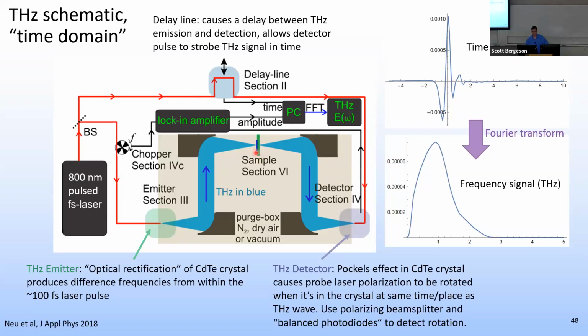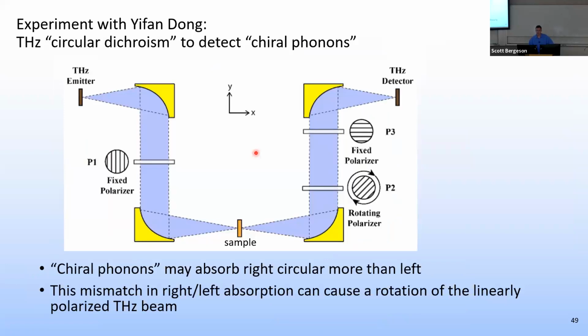We're interested in this because one of the thoughts is that these chiral materials will have what are called chiral phonons. Chiral phonons are oscillations of the atoms in the material that form a rotational pattern as they oscillate. Chiral phonons may absorb right circular terahertz more than left circular terahertz, and this mismatch between right and left absorption can cause a rotation of a linearly polarized terahertz beam. So that's the type of thing we were looking at: rotation of the polarization of the terahertz beam.